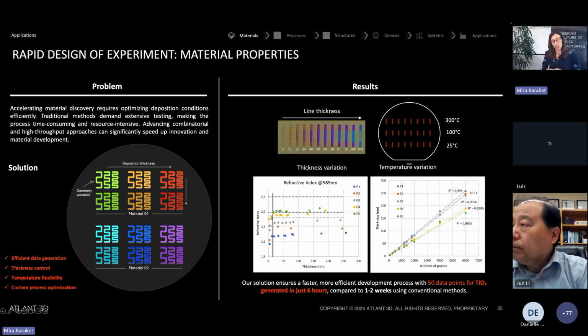So in this case, we are talking about titanium oxide, where we take our wafer and we have deposited multiple lines with multiple thicknesses in the rows that you see here, but also we have processed our material at different temperatures. And what we have ended up with, with that technology, is an efficient development process. So we were able to get 50 data points of titanium oxide generated in just 6 hours. If you were to compare that with normal technologies, this would have taken 1 or 2 weeks using the conventional methods.